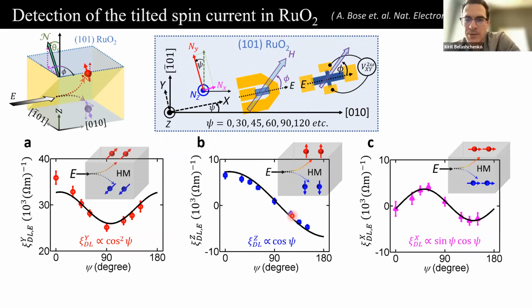Do I understand correctly that if you did that, you would expect a random amplitude centered at 0, sometimes positive, sometimes negative, with some range? Yes, I understand the point, but I don't know what will happen in that case. There could also be a possibility that, since we have a ferromagnet adjacent to this antiferromagnet, ferromagnetic-antiferromagnetic coupling could stabilize essentially an antiferromagnetic domain, preferably. So that can also happen.